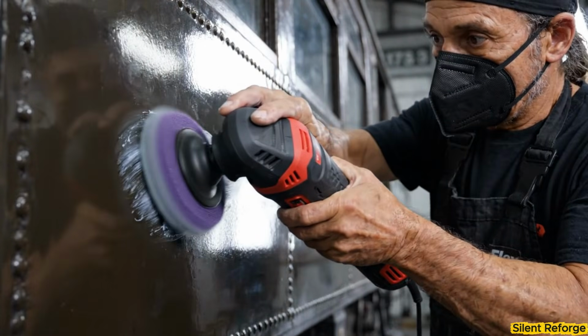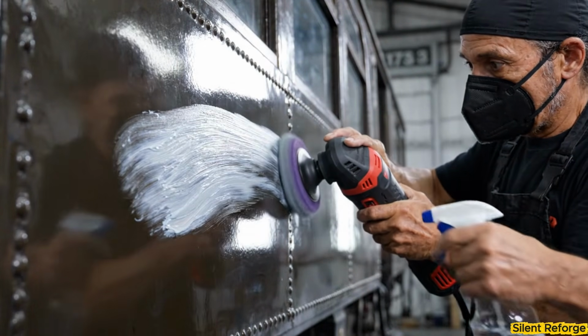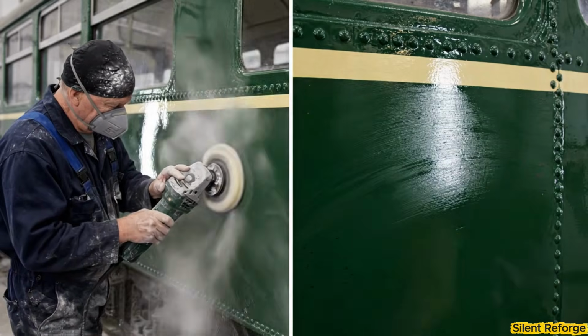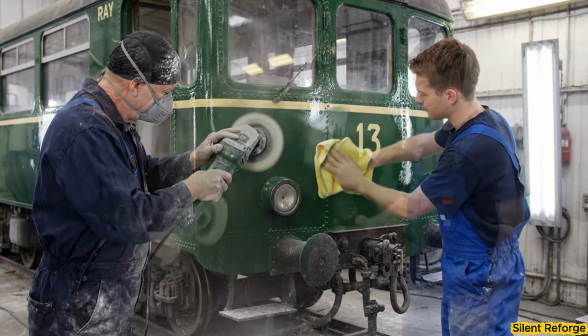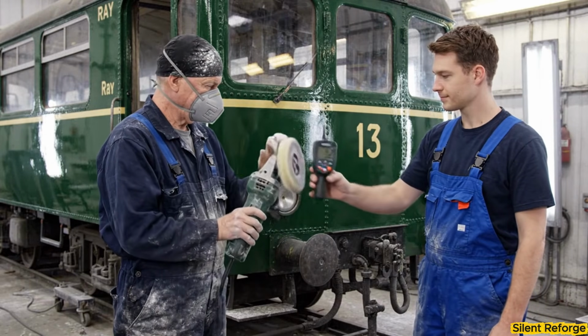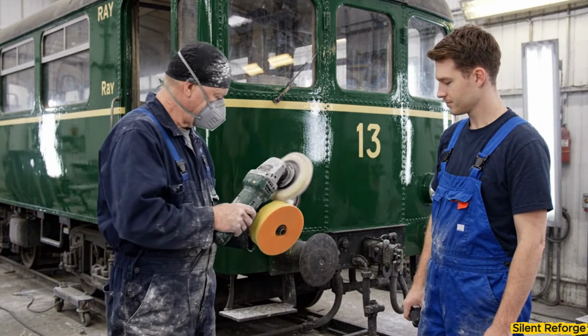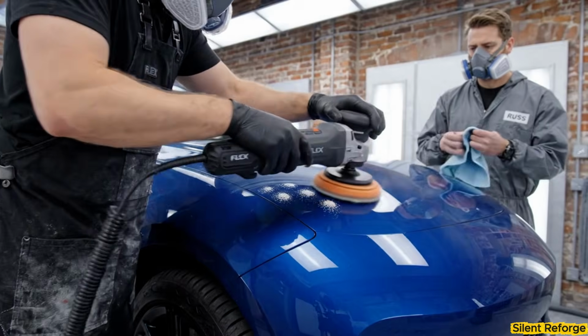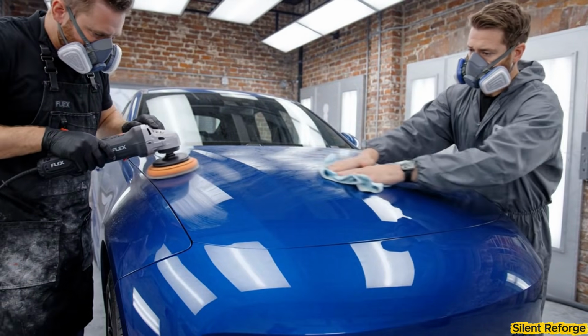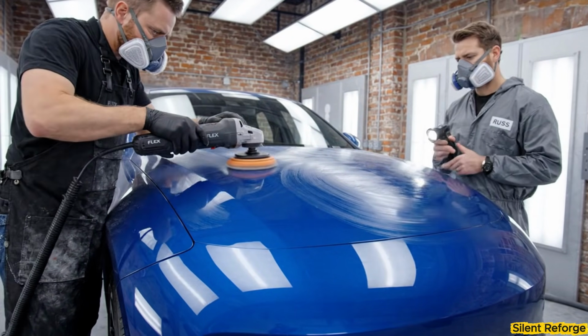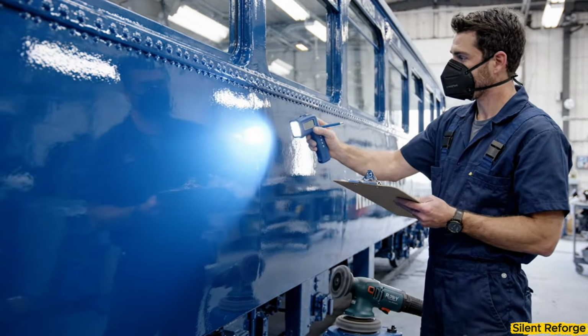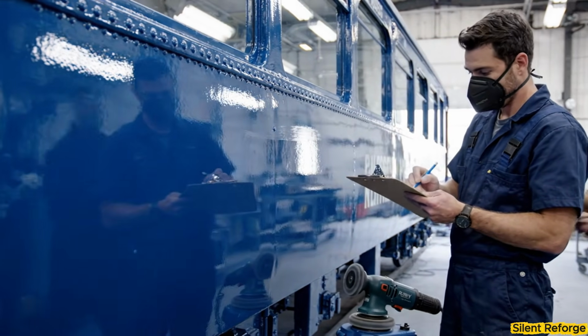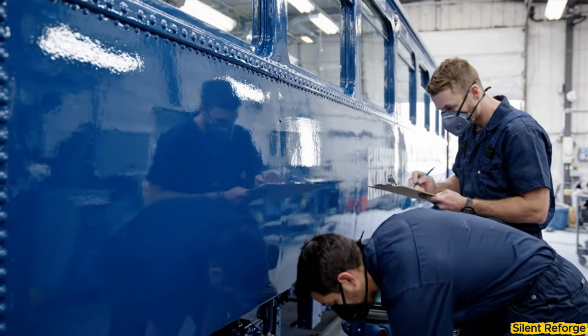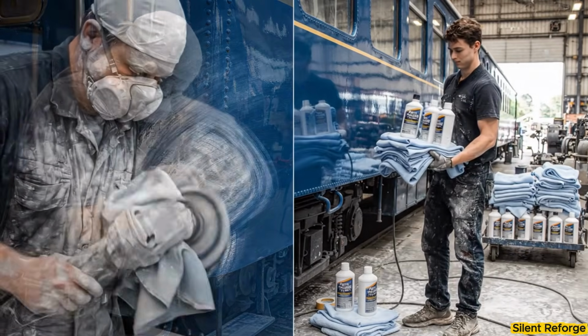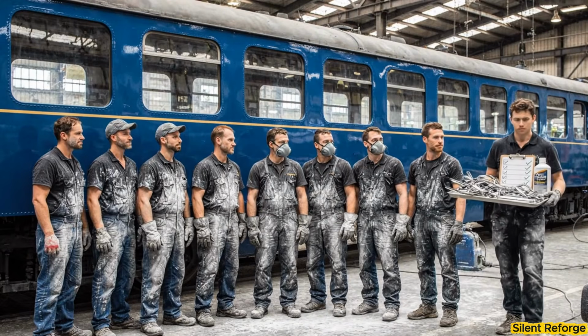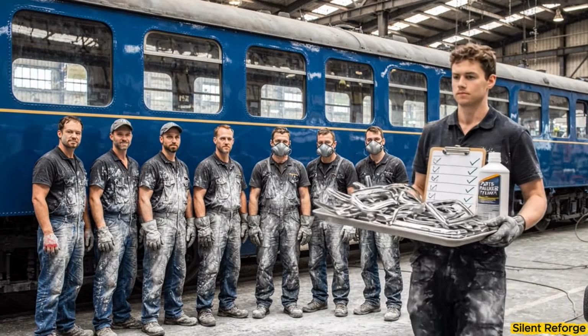Paint correction is the process of removing the outermost layer of clear coat to eliminate orange peel texture, dust nibs, and defects. The diminishing abrasive particles in the compound are aluminum oxide crystals suspended in a lubricating oil emulsion. The finishing polish uses submicron abrasive particles suspended in a water-based lubricant that generates less heat than the oil-based compound. A show-quality finish requires 90+ gloss units, low orange peel, no visible defects, and adequate clear coat measurements. Across the 8 panels of the left flank, the polishing process has removed a total of 0.5 grams of clear coat material.